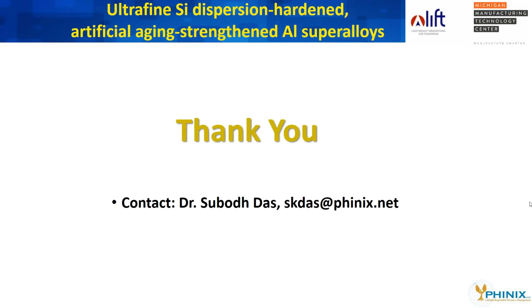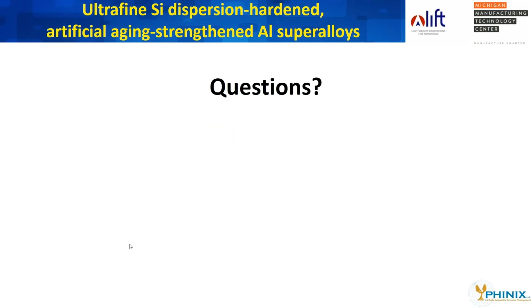Well, I did have one question. I know we're running up at the top of the hour, but someone wanted to know how did you avoid the solidification of the coarse primary silicon particles? They may have missed that question, but how did you go ahead and avoid that? There are two factors. One is if you do it fast enough, it doesn't have enough time to nucleate and form. So the high solidification rate is one key aspect. The other aspect is the right amount and the right type of modifier,